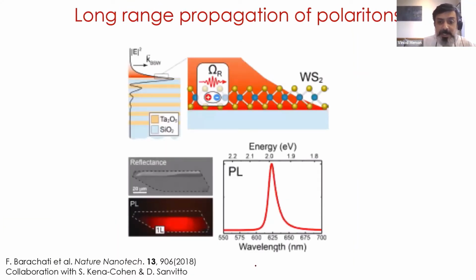There were two other groups that reported very similar work. So the take-home message here is that the polaritons inherit this property called valley polarization. The other interesting property of these systems is the fact that you can make them propagate long distances by coupling them to a very photon-like mode. So here we don't even have a cavity. We just have a distributed Bragg reflector. You have a mode that gets created at the edge of this system called the Bloch surface mode. And these Bloch modes can be used to couple to the 2D materials because there's a gradient of the field.